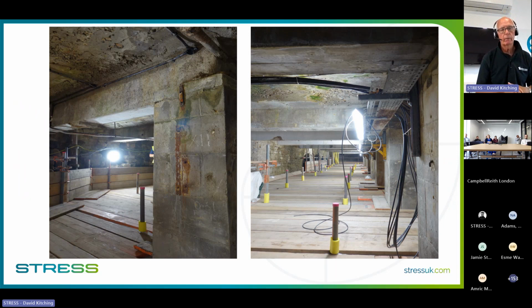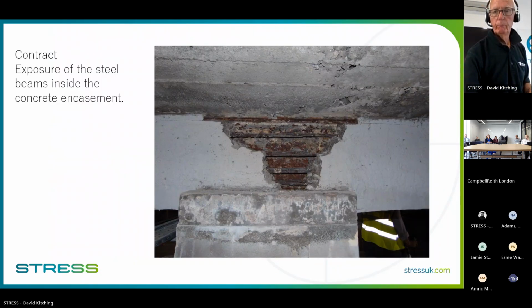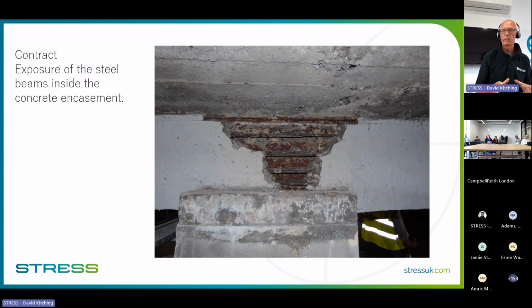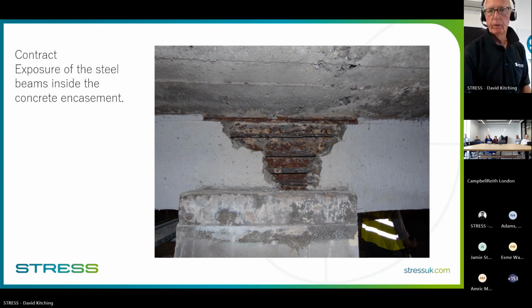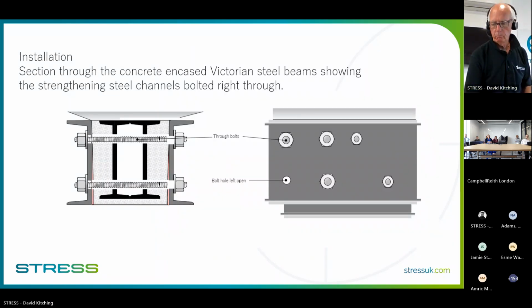So you can see the Victorian concrete there, a bit honeycombed, tested, absolutely perfect, not a problem with it. But the beams were starting to corrode at the ends. We took some of the concrete off over one of the center piers just to get an idea of how far this corrosion had gone. And in fact, we found it really wasn't bad. It was, yes, rusted, but it wasn't flaking in any way. And you will see that in a minute.